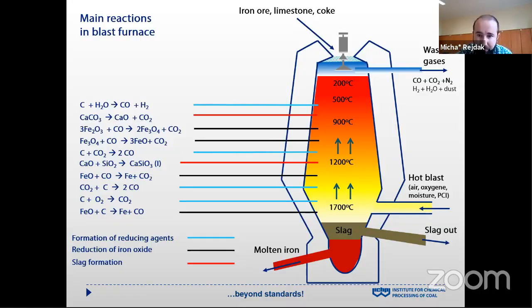At the bottom of blast furnaces, there are hot blast nozzles. The oxygen in the air on contact with the coke generates carbon dioxide. Then the carbon dioxide on contact with the hot coke produces carbon monoxide, in the Boudouard reaction. The carbon monoxide produced in this way is the main reducing gas for the reduction of iron-bearing ores to liquid iron.